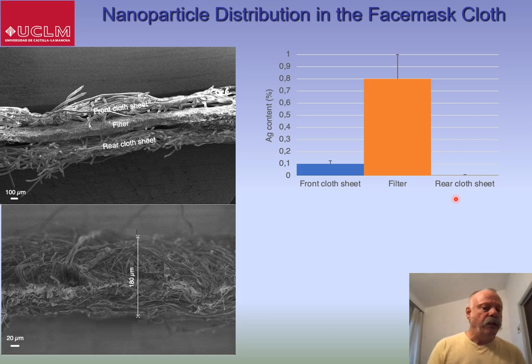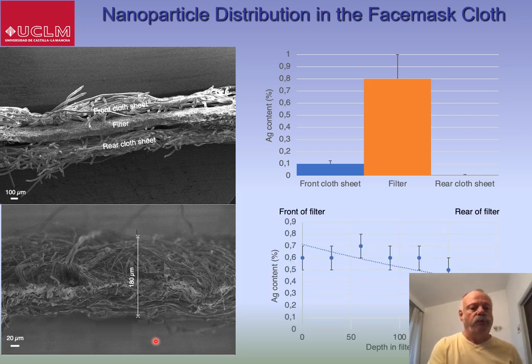Looking in more detail at the filter itself, this slightly higher resolution SEM image shows a very high density weave with a low density weave cloth either side. And again, looking at EDX data for silver through the depth of just the filter this time, you can see there's a steady decay of the amount of silver as you go from the front to the back. But basically, the entire filter is coated with silver nanoparticles throughout its volume.